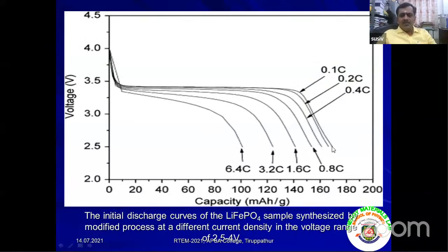See, at 0.1 C, it attains 170 milliampere hour per gram. What is the theoretical capacity of the material, LiFePO4? It is 170. So they have attained 170. We have also attained 170 milliampere hour per gram by using some carbonaceous material with sulfur.